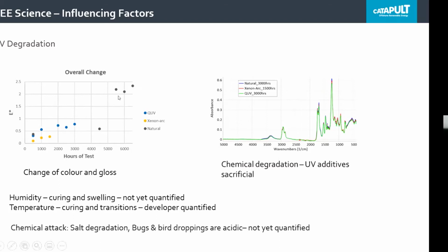So what you can see here is that Xenon Arc actually follows the natural weathering quite closely. Ignore the 3 measurements at the top because those are actually from a leaf falling on the surface of the sample. QUV is quite damaging, but the actual requirement after 3,000 hours is a delta E change of 1, and it's just very difficult for a lot of materials to meet. That is basically because, particularly in coatings, to meet UVA requirements, people include titanium dioxide as a filler, which is sacrificial. But the titanium dioxide's presence actually affects the rain erosion performance, so it's a trade-off between the two.